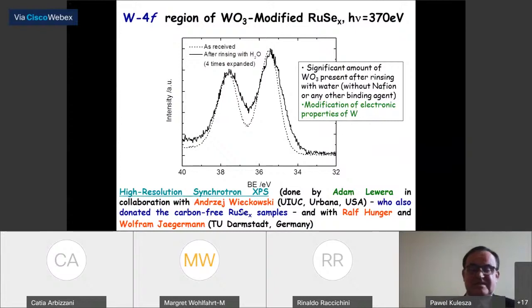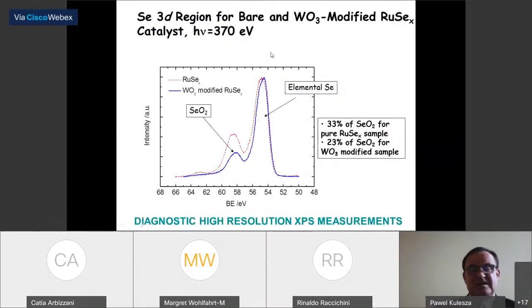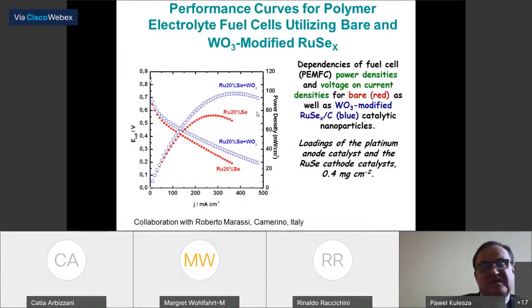Well, when we did experiments, it was also part of a collaboration with Andrzej Więckowski, and Adam Lewera did an experiment together with Wolfram Jaegermann, showing that there's no change on the ruthenium side, but there's a change on the selenium side. Selenium is becoming more, if you can say, metallic. Also, it's not a metal in a sense, but in very small amounts, it behaves more like a metal. So in a sense, we are making ruthenium indirectly more metallic. And there was also improvement in a fuel cell using ruthenium selenium. So this was done actually in Camerino, that experiment.